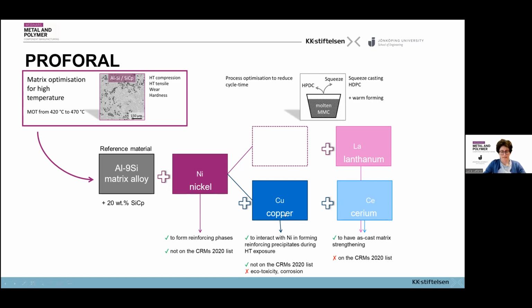Then we decided to also add copper because it is also known to interact with nickel in reinforcing precipitates during thermal exposure. It is not on the critical raw material list, but the challenge with copper is that it has issues with corrosion and ecotoxicity. So if it is dispersed in the environment, there are some regulations that limit its use. But to keep all our possibilities open, we decided to also go for that.